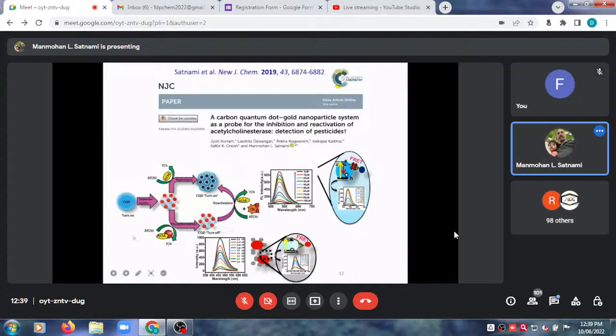Okay, see, we prepared carbon quantum dot through hydrothermal route, and in this carbon quantum dot we added gold nanoparticle. The fluorescence intensity of carbon quantum dot is decreased. Why did this happen? Because the energy of carbon quantum dot is transferred to the gold nanoparticle. Then fluorescence quenching is happening with this carbon quantum dot.